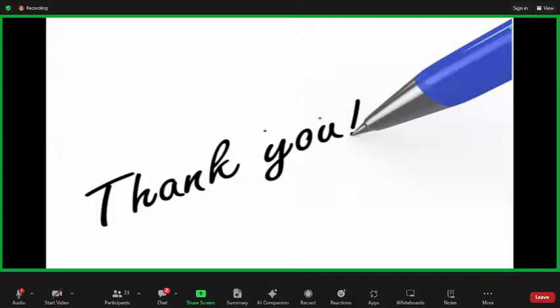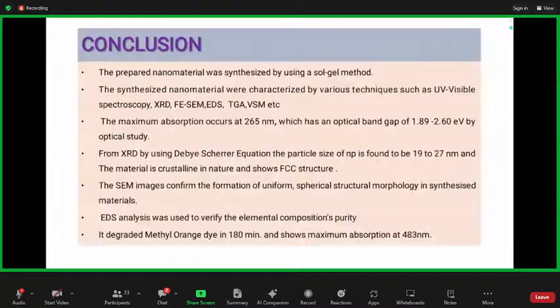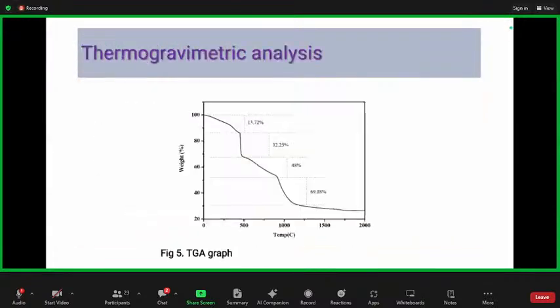But from the TGA graph, please show your TGA graph here. Yes, sir. In this TGA graph, which is the calcination temperature? You analyzed your sample by TGA, okay? What is your temperature of calcination from the TGA graph? From this TGA graph, we are getting 4 steps of decomposition, sir. And after around 1250, the temperature remains constant. It means around 1250 the decomposition is completed, as per my knowledge.